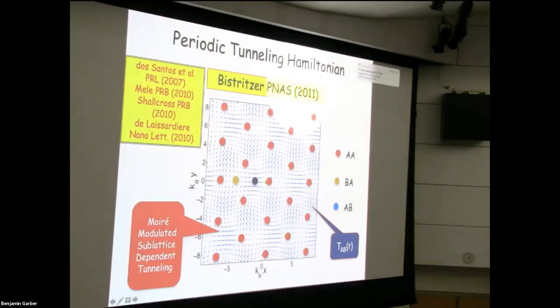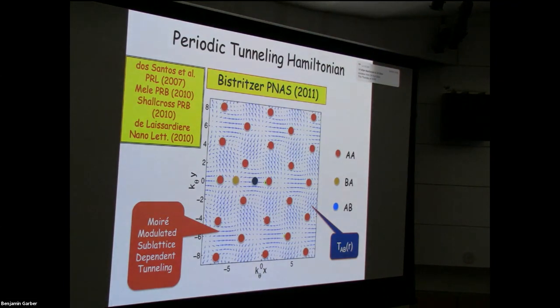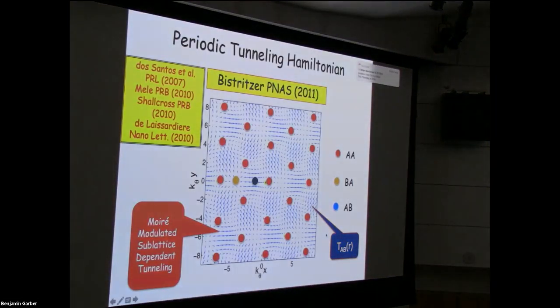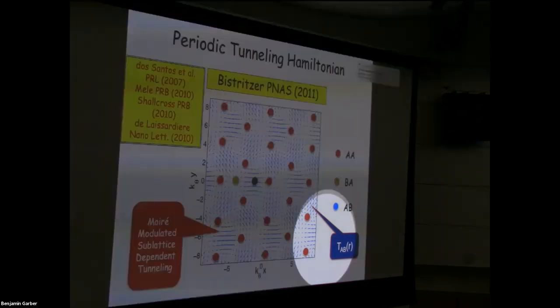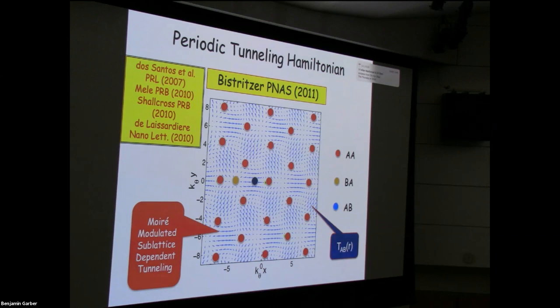This picture is from a paper I wrote with Rafi Bistritzer on this topic a long time ago. And what it's showing is just one complex number, which is a tunneling amplitude from some particular sublattice, let's say the B sublattice of the bottom layer to the A sublattice of the top layer. So it's a complex number represented as a little arrow with a length and a direction. When the arrows get small, it means the tunneling goes to zero at certain points in the stacking arrangement, which you kind of know by symmetries, for example. And the red points here are the AA point stacking arrangements that I discussed earlier.